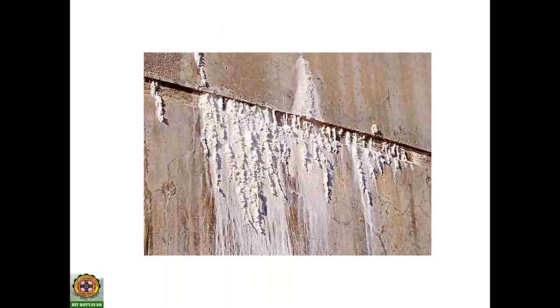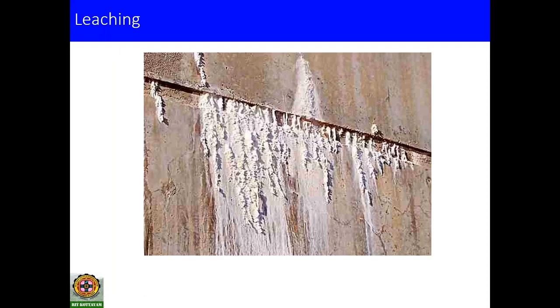Now these white patches, what does this indicate? Efflorescence. Yeah, efflorescence. Right, good. Or it's leaching. How does leaching happen? When soft acidic water, or soft water, or normal water itself enters the concrete and comes out, it can dissolve the calcium hydroxide. And when the calcium hydroxide is coming out, it can react with the carbon dioxide, forming calcium carbonate. And this calcium carbonate is what is shown as the white patches. So this is again a type of deterioration of concrete.